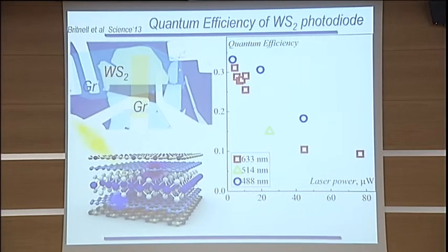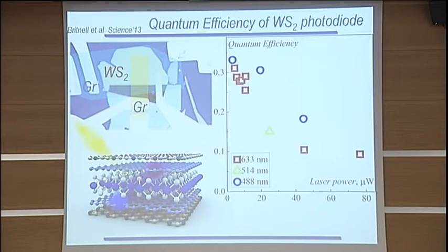Surprisingly, I mean, originally we just played with it a little bit, but surprisingly, the quantum efficiency of those devices is quite good. That device is not optimized at all, and the external quantum efficiency is already 30%, which is quite an appreciable number, especially considering that we have an extremely thin layer of tungsten disulfide there, only say 3-4 layers, so it's quite transparent.